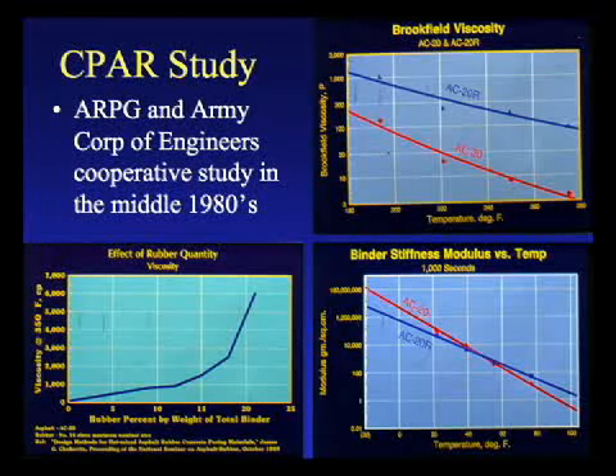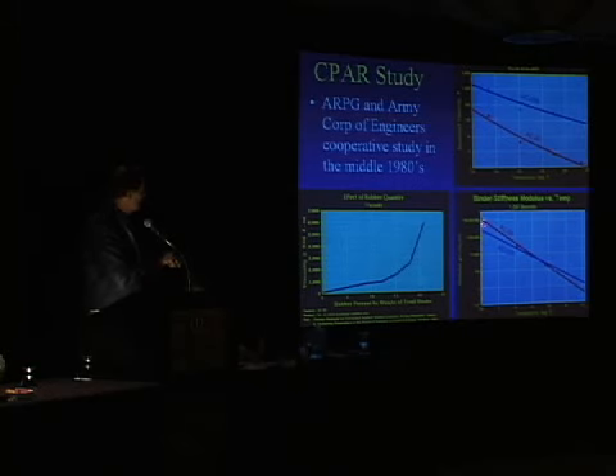These slides just give you an indication of changes in the different types of properties that we look at in binders. This one here is the viscosity versus the temperature. And basically what it shows you is that at the same temperature, you can see the very large change in viscosity of the product. Over here, we see the temperature susceptibility of the material. In all of these, the blue line is the rubber. Now, what is important is that an ideal binder would have a horizontal line. That means it would perform the same in cold climate as it would in hot climate. Unfortunately, we don't have a binder like that.